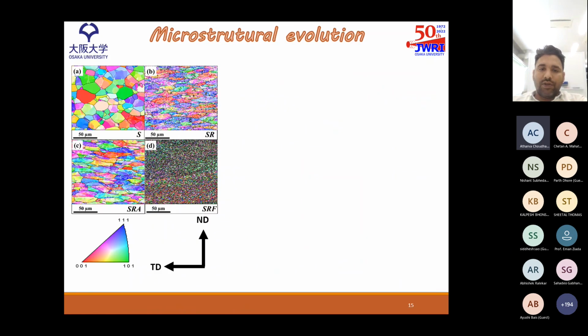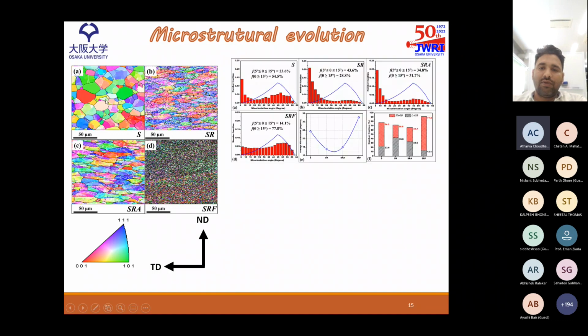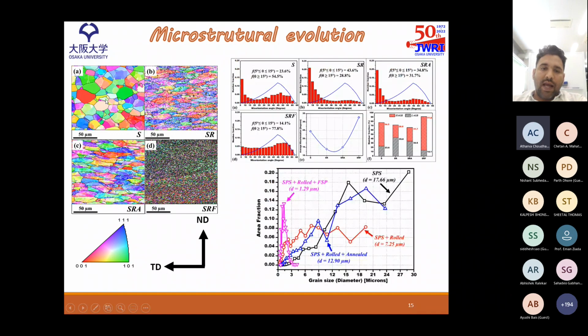Now coming to the microstructural evolution, we can see that this is the spark plasma sintered billet. The grains are equiaxed and recrystallized. A very fine grain structure is obtained here, which is around 17 micron. And on rolling, the microstructure transforms and low angle grain boundaries are formed. These are typical elongated grains, which we can see here. And the grain size reduced to around 7 micron because of the subgrain structure formation.